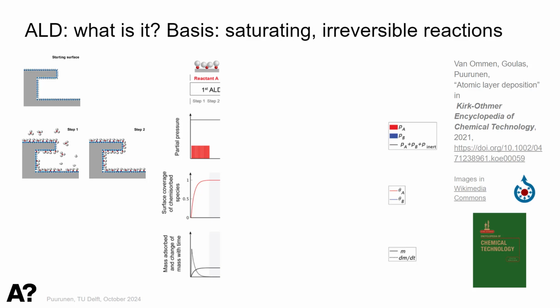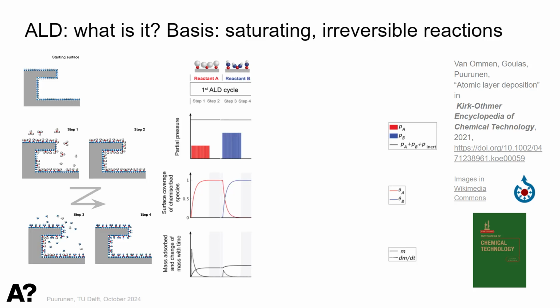And if you look at things as a function of time, like mass change, it happens quickly in the beginning, and then when the reaction is completed, nothing happens anymore. So this is not a continuous process, it's a transient process. Then you bring in the reactant B, and it reacts with the surface. Again, the extras are purged or evacuated. The reactor brings the partial pressure there, and the coverage of the first species goes to 0 ideally, and the second species goes to 1, and again you are adding or sometimes removing mass from the surface, and you end up growing a little layer.